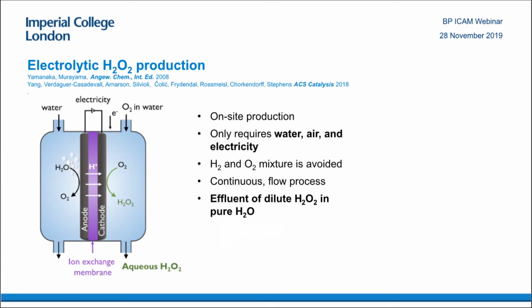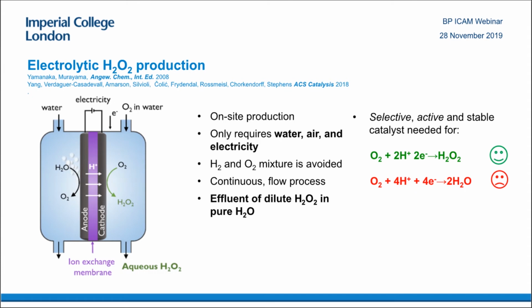So it turns out you can actually make hydrogen peroxide using electrochemistry. And if you could do it in this kind of configuration I've shown here, you can make it on site. You only need water, air, and electricity. You avoid reacting hydrogen and oxygen directly. It's a continuous flow process. And now you get hydrogen peroxide at exactly the concentration you want in pure water.